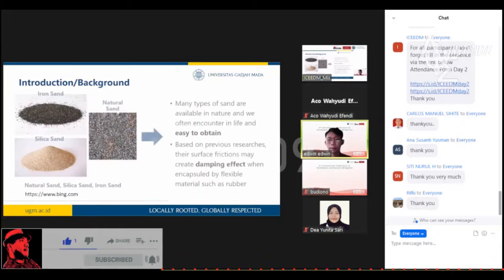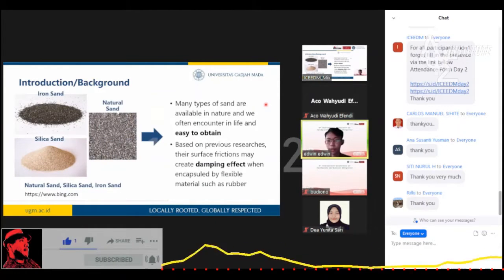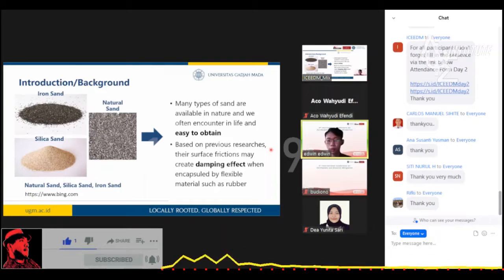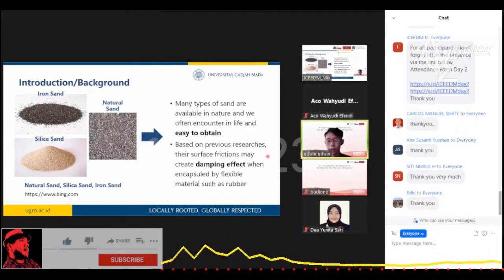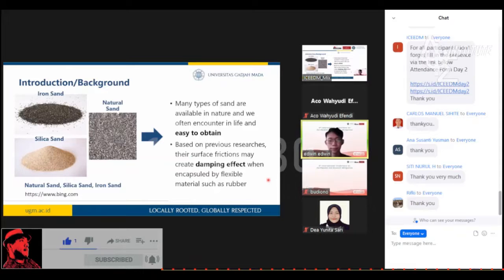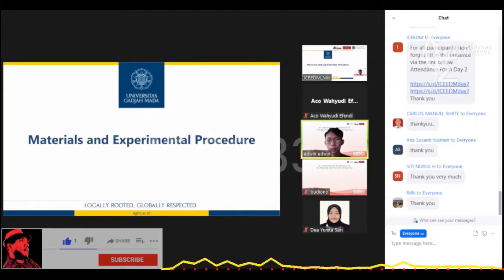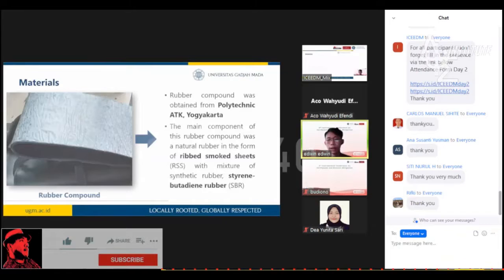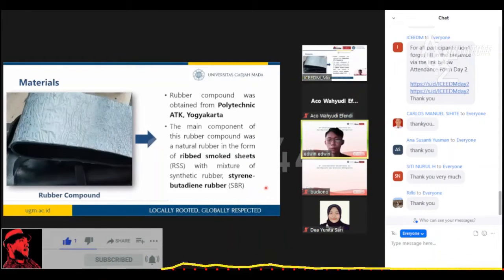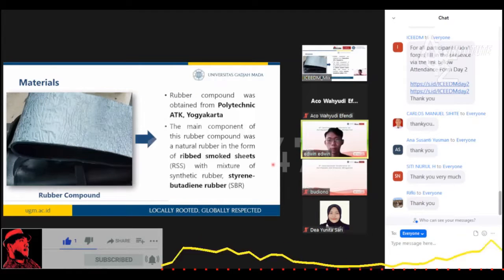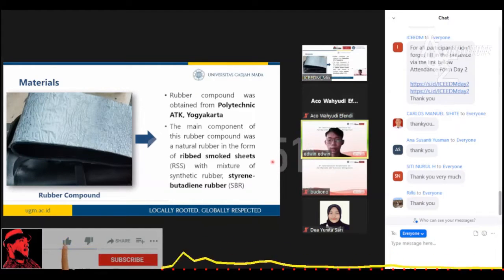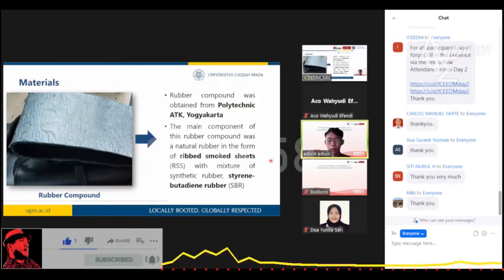And on the other hand, many types of sand are available in nature, and we often encounter them in life, and it is also easy to obtain. And based on previous research, their surface friction may create a damping effect when encapsulated by flexible material such as rubber. Next, I will explain about materials and experimental procedure used in this research. The first material was rubber compound that was obtained from Polytechnic ATK Yogyakarta. The main component of this compound was a natural rubber in the form of ribbed smoke sheets with a mixture of synthetic rubber or styrene butadiene rubber.